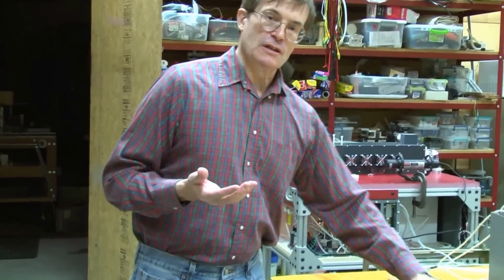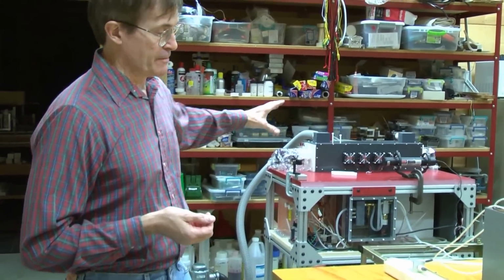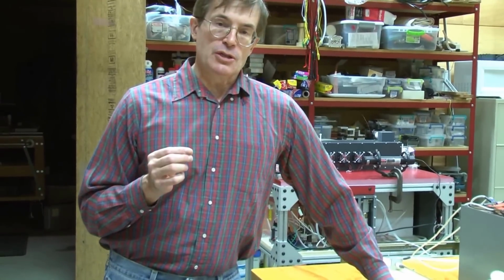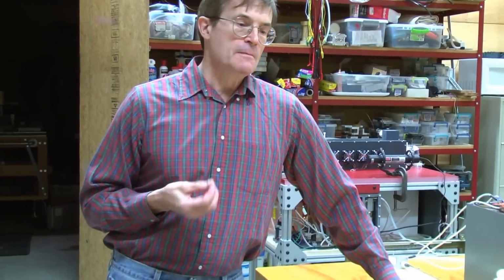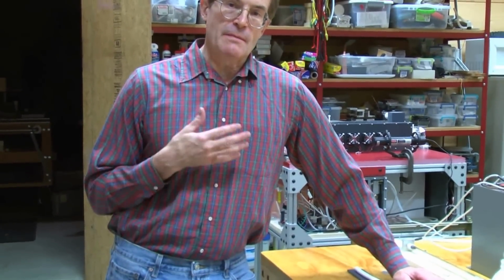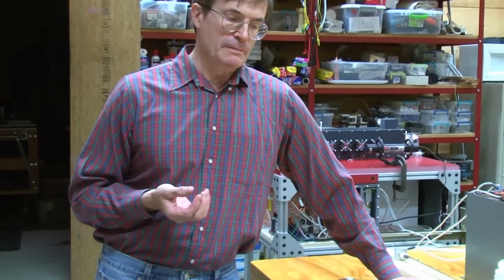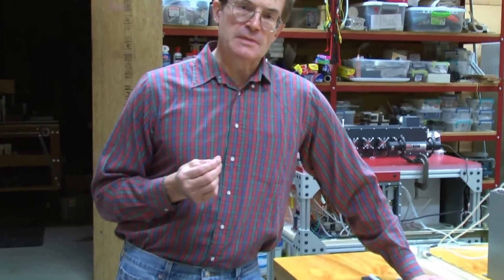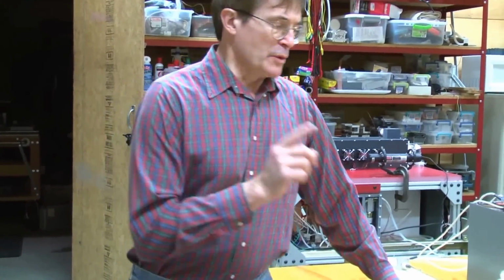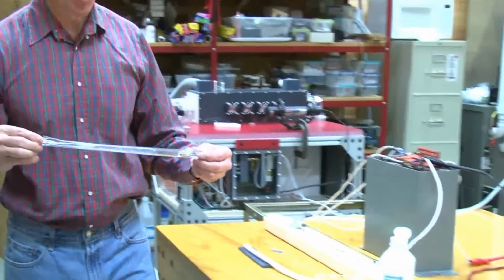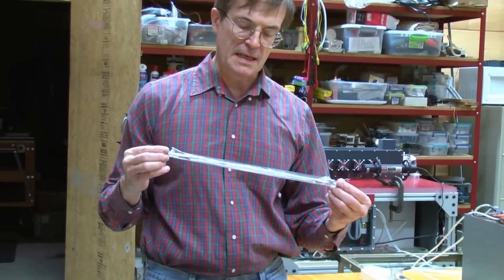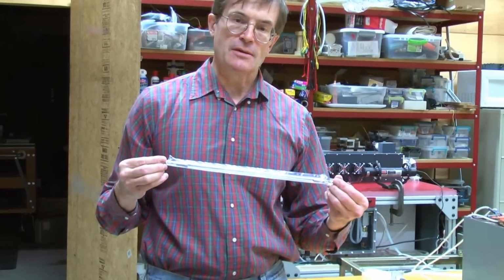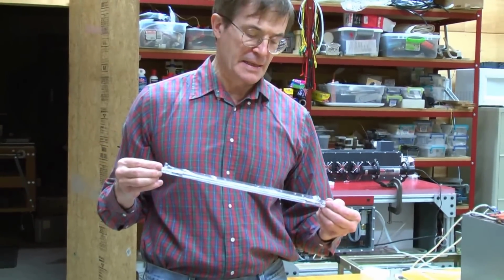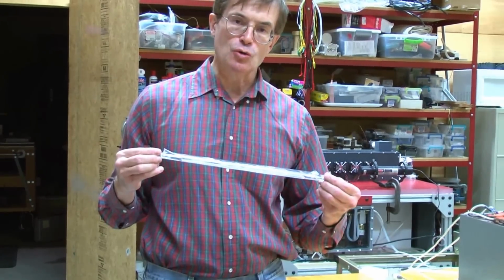When you begin to drive the lamp harder and harder in order to produce enough energy for, say, a very high energy laser, the random thermal emissions that are also occurring become more and more dominant until eventually at the very highest energies you can't even see the xenon lines anymore. It doesn't matter what the gas is that you're using to produce the output. And at that point, the xenon becomes a disadvantage of the low pressure tubes. When they fill these xenon lamps to maybe 200 to 400 torr of xenon, they need to do so there's enough atoms in there to catch the electrons and to emit the light. But it also increases the impedance of the tube substantially.